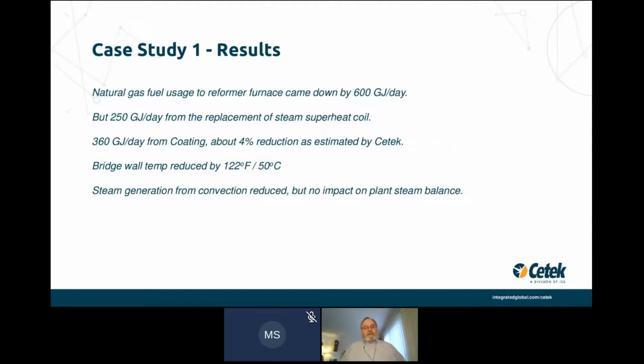the gas usage came down by 600 gigajoules per day, but while we were celebrating, they told us that 250 gigajoules per day of that came from the replacement of steam superheat coil. So it was calculated that 350, or 360, sorry, gigajoules per day came from the coating, which was about 4% reduction, which was what we'd estimated in the first place in our evaluation. We also reduced the bridge wall temperature by a very nice amount, since more heat was now being absorbed in the radiant section. The steam generation from the convection section was slightly reduced, but it didn't have any impact on the plant steam balance. They were still happy with that result.